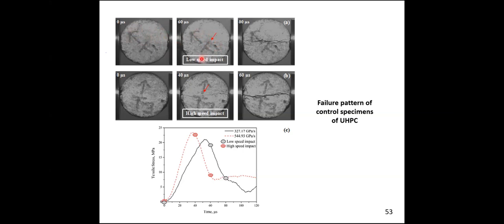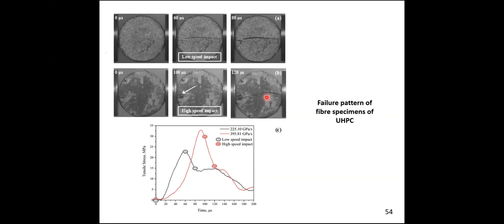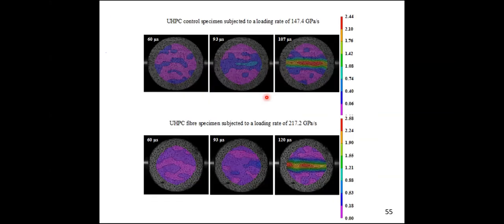So at low speed impact, you could see a crack initiation, and then the crack has grown. You can see a crack growth. Again, at high speed impact also, you could see there are more number of cracks formed, and they got propagated. You can see from that figure. So this is what I wanted to convey.